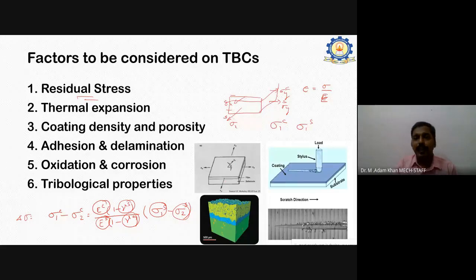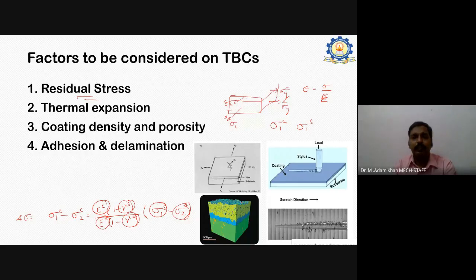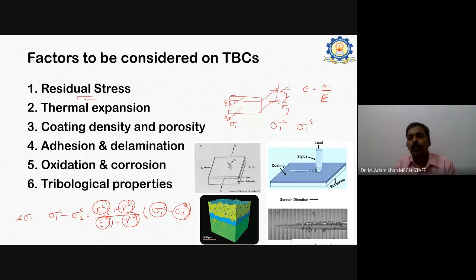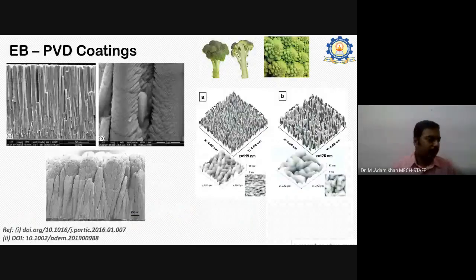At the same time, we should take care of the thermal expansion. As I mentioned in the earlier slide, you have to take care of the thermal expansion rates of the substrate material, coating, and bond coat, all three together, before making it. At the same time, you should note whether the adhesion and delamination of the coating is not compromised. For that, we have to go for proper scratch tests, or an abrasion test or indentation test can be done. Oxidation and tribological properties are the main motto of the research involved in thermal barrier coatings.